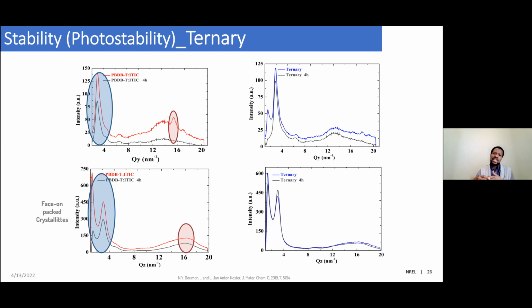And the good thing we observed is that when you begin to introduce PC70BM, you are able to at least preserve this kind of crystallinity and packing over time. Though it degrades, it's not as pronounced as in the ITIC system.